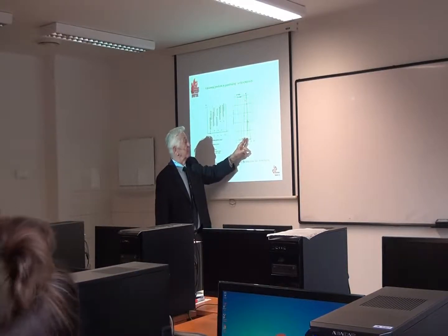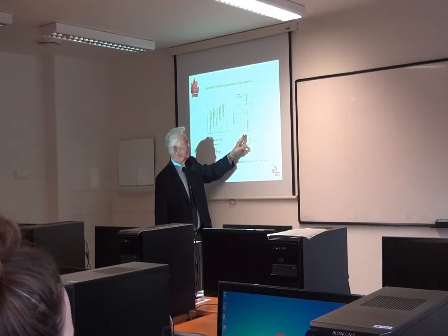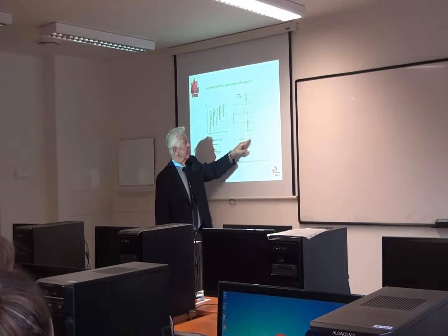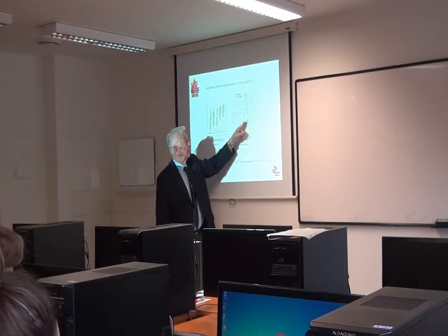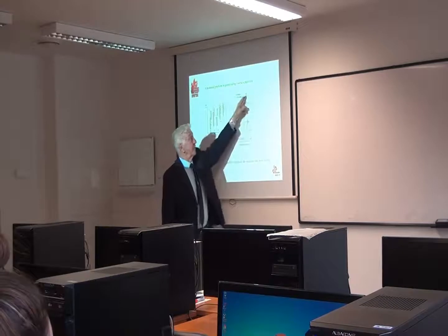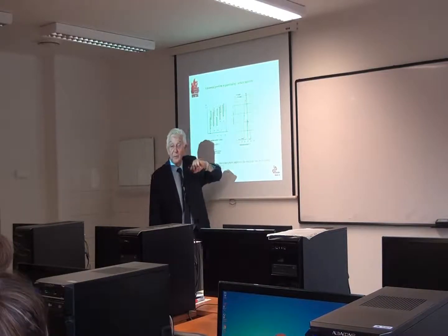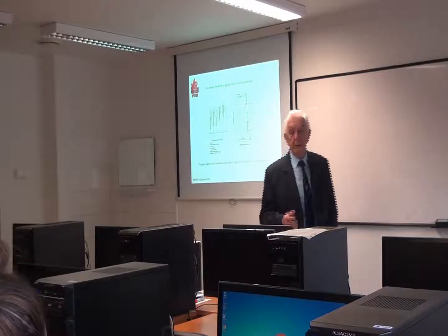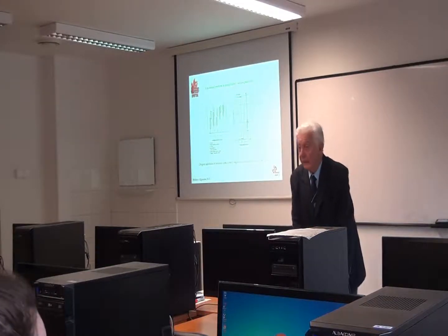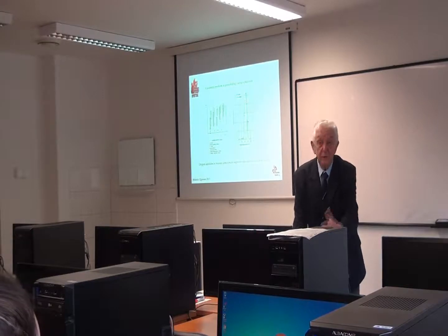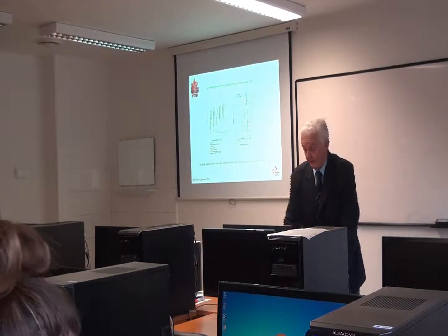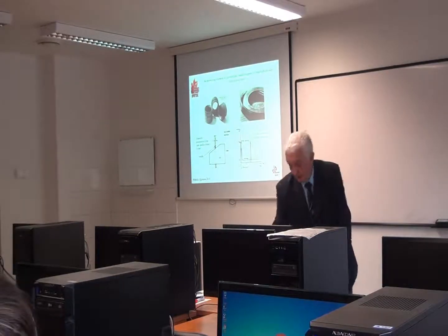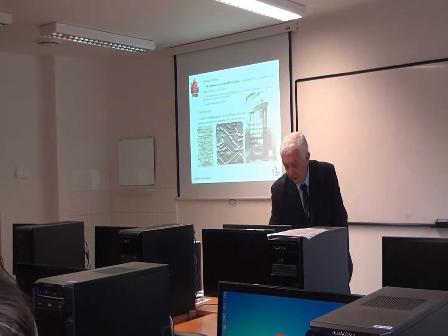What I have shown you here is the undissociated ammonia, the ammonia gas of nitriding, showing the reaction rate, and you see the reaction rate is much, much lower when we have no oxygen in the atmosphere than when we have oxygen in the atmosphere. So that was the first thing which we learned, that when we want to activate nitriding, we have to solve in a way or other the presence of oxygen. So, well, I can go back a little bit.